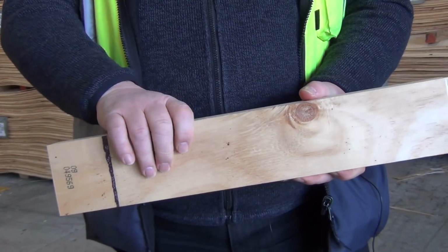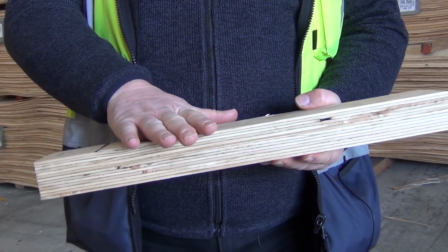We've got a 35 MPa compressive strength on the end grain, same as concrete. We've got a 10 MPa compressive strength on the sides. So you have to think outside the box about how it's going to work. You have to think a lot more about the connections and how that's going to happen.